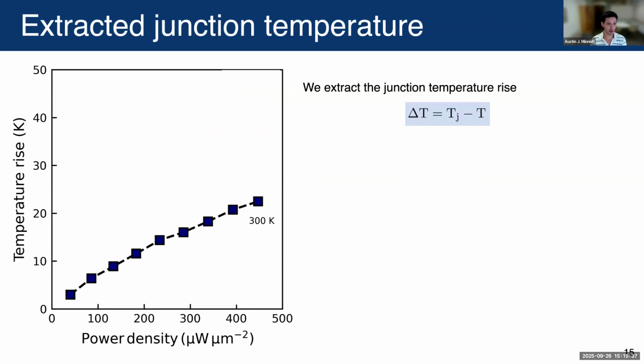Okay, so now we can be more quantitative. Using the Schottky thermometry technique, we can extract the temperature rise on the y-axis versus the power density on the x. And at room temperature, we see that it's approximately linear, the temperature rise in the power density, which is expected. And that temperature rise is only maybe a few percent of the base temperature, 300 Kelvin, which is again reasonable at room temperature.